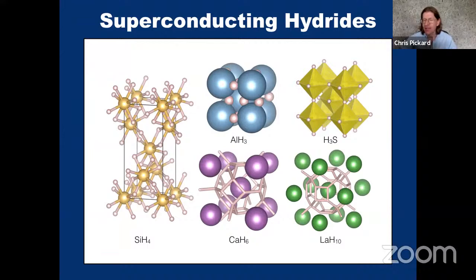Experimentally, it wasn't. And it turned out for quite interesting reasons. At the simple BCS level of theory, it should be a superconductor. But when you take into account anharmonicity in the phonon modes, that superconductivity is suppressed. So I kind of lost heart at that point. I didn't do too many more calculations of the hydrides, but luckily my excellent colleague in Jilin University, Yanming Ma,